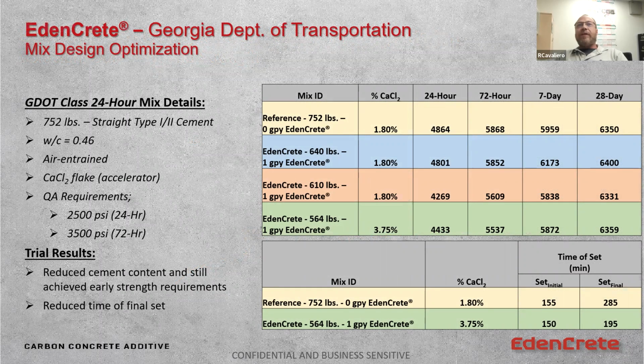So we then worked with them to demonstrate that we could help them optimize their mix. Their standard mix is 752 pounds of cement per cubic yard. It's a 0.46, and it has no EdenCrete. So we ran testing and tested compressive strength. We then dropped the cement 112 pounds, added 1 gallon of EdenCrete. We saw that the strengths were comparable. So we kept going down, dropped another 30, kept the EdenCrete, dropped a little bit.